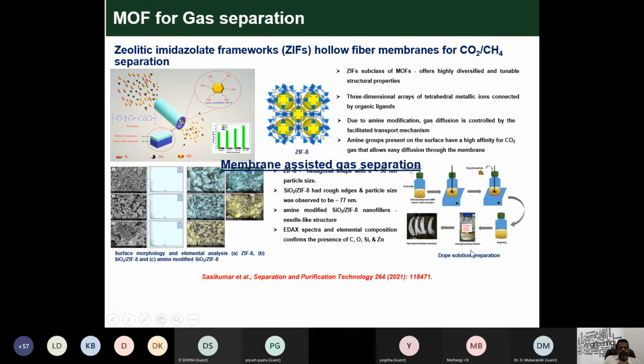We use hollow fiber membranes made using a dope solution. When I talk to membrane technologists, they ask how you can scale up or commercialize these materials, and whether you are using flat sheet or hollow fiber. But we have proved that reproducibility and commercial viability of this kind of MOF incorporated polymer membrane is possible. You can develop 1,000 or 2,000 hollow fiber membranes applicable for commercial carbon dioxide or methane separation. So we proved that ZIF-8 is commercially viable for gas separation.